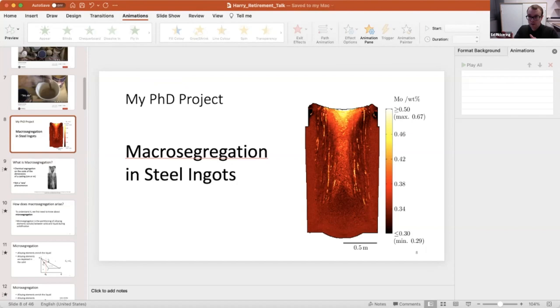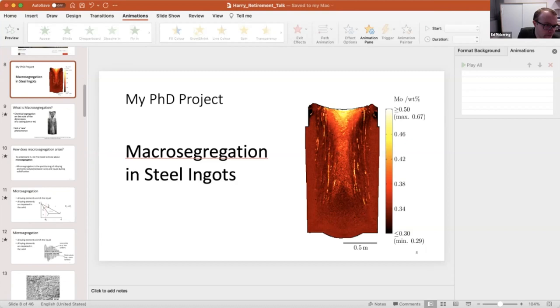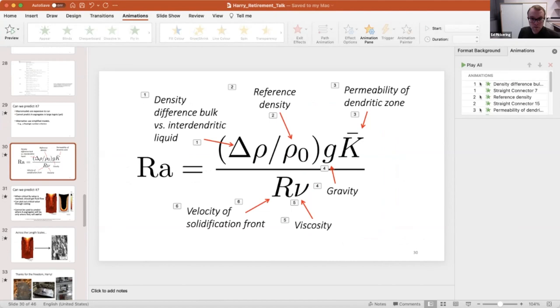The other thing, of course, is that you can try and live with it by making sure that none of these features intersect the surface. So that's another way of designing that in, and try and predict where they are and design that in. You can try and eliminate them as well. If I go back to the Rayleigh number, you can try and eliminate them by, for instance, making a hollow casting. And a hollow casting, if you're making a pressure vessel, is a really good way to do things, because then you increase the solidification speed, and that reduces the amount of time you have for the segregates to form.